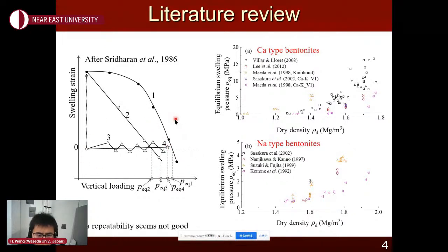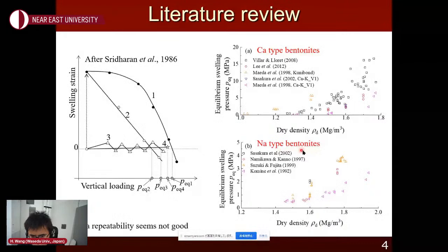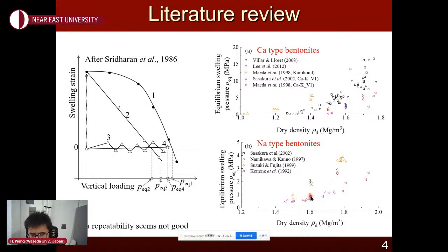Of all four ways, recently for compacted bentonite, usually the third and fourth ways are very popular. But one question is that it's not easy to measure the swelling pressure very accurately. For example, this is the so-called final equilibrium swelling pressure, and this is the dry density. You can see that even under the same dry density, the data scatter very much. This is for the so-called calcium-type bentonite, and for sodium bentonite also, under the same dry density, even with the same experimenter, the data are very scattered. So we considered how to get a good testing method to measure this pressure.